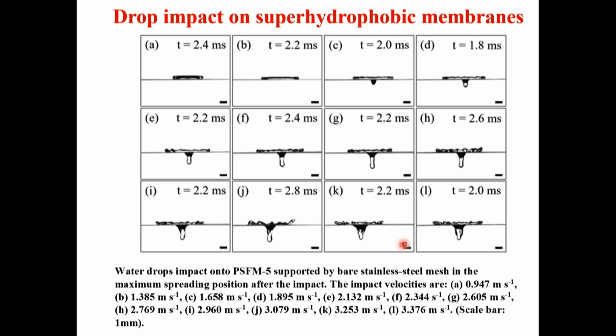By the way, it looks like you essentially made a hole in the membrane, but there is nothing like a hole. So you can inspect these membranes after this type of penetration, and you'll find them absolutely intact. So all that is coming through is coming through the pores, and the membrane is absolutely undamaged.